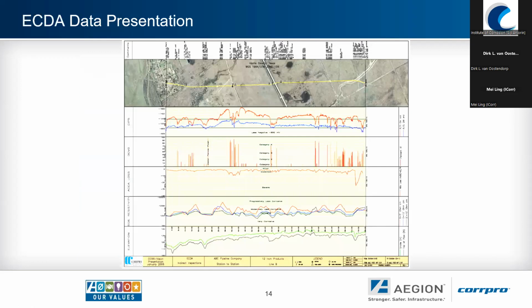And then from a geospatial standpoint on the back end, one of the important things is being able to have the data in a format where it can be aligned and then geopositioned. In this case, it's a typical example of usually the data results. We have a system that converts it into multiple bands. And on top is showing the data on a Google Earth background. So with the CIPS data on the top, we're able to identify areas where there are apparent coating anomalies, areas where the potentials do not meet criteria, the DC voltage gradient below that. In this one, there's also current attenuation testing that was done, and then soil resistivity as well, along with the topography of the pipe at the bottom. So this is a snapshot of how all of the data can be accumulated and assimilated very rapidly, since it is geoposition data.